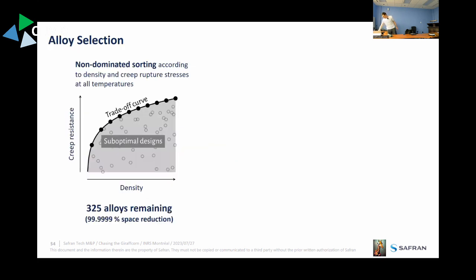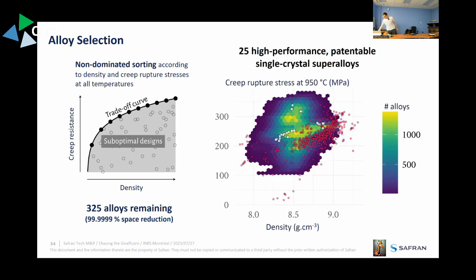Then 200,000 alloys is a bit too much. So we tried, and I'm going to accelerate, to select through non-dominated sorting, which is similar to what is used in genetic algorithms. And I'm going to talk about genetic algorithms just after that. So for the record, we validated predictions on these alloys for most of them, not all conditions, not all temperatures, but generally they gave us very interesting alloys with mechanisms that we did not expect they had.